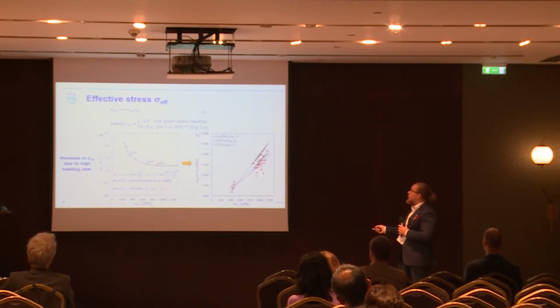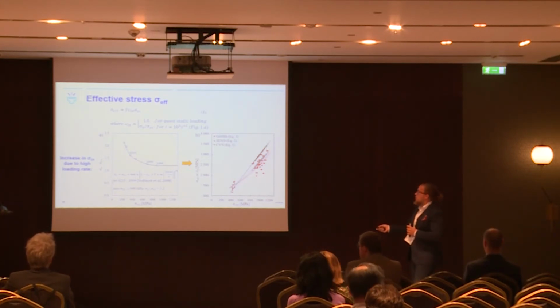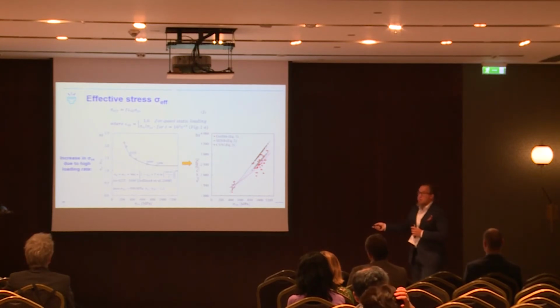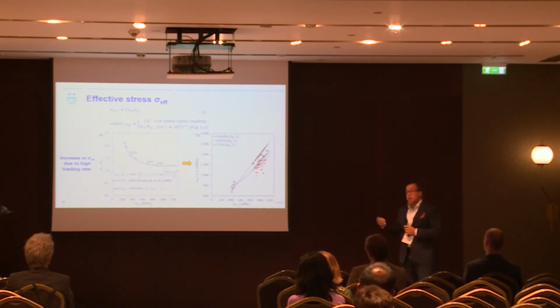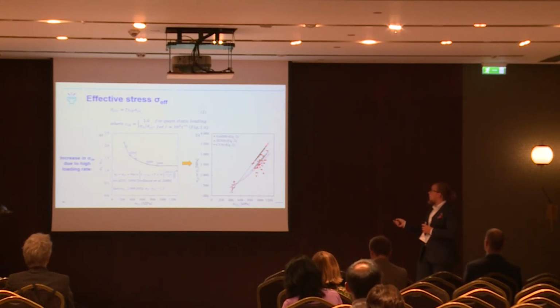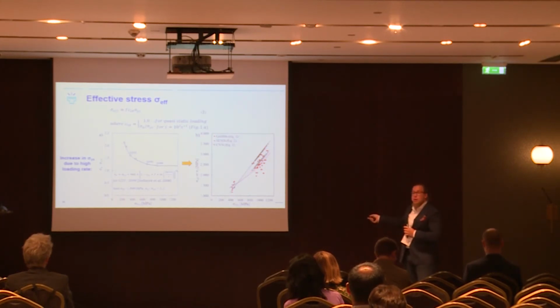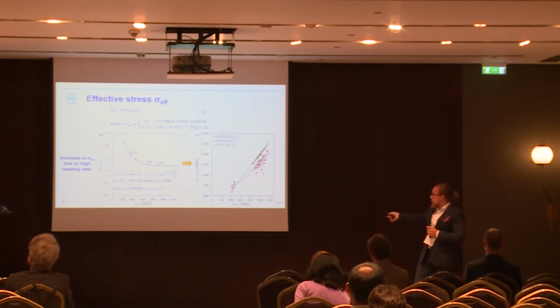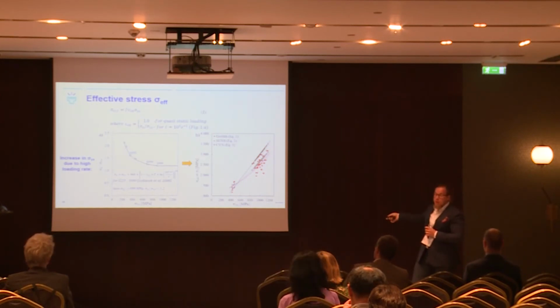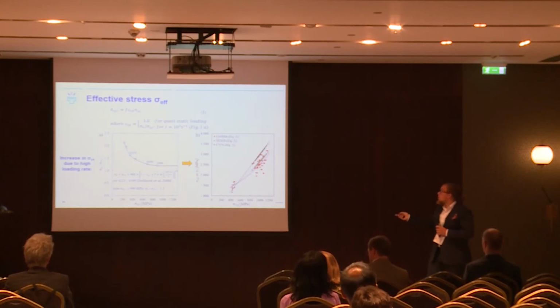And because of insufficient data, we have used a constant 1.2 for materials with room temperature strength of 900 megapascals and more. And with this effective stress, we see that in the case of pre-cracked specimens, it forms an upper boundary to these materials that have been calculated with this criterion of fracture stress. And when the crack size has been taken as the effective coarse grain size or the cleavage fracture unit size, then they do coincide in the cases that we have studied under the microscope.